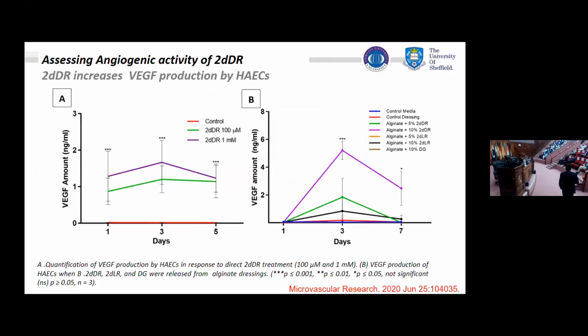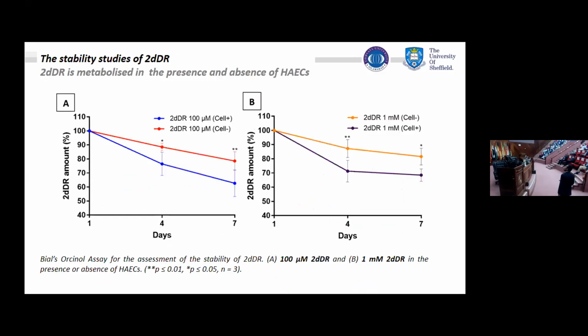At this stage, we were interested in learning how this tiny sugar molecule supports blood vessel formation. So we took the cells and treated them with 2-deoxy-D-ribose, 100 micromolar and 1 millimolar, and also with these sugars when released from a variety of the dressings. What we saw is that these sugars resulted in an increase of VEGF. And we know that VEGF is responsible for new blood vessel formation. So from here, we got confirmation that 2-deoxy-D-ribose supports new blood vessel formation by upregulation of VEGF.